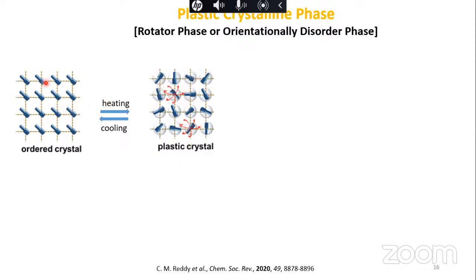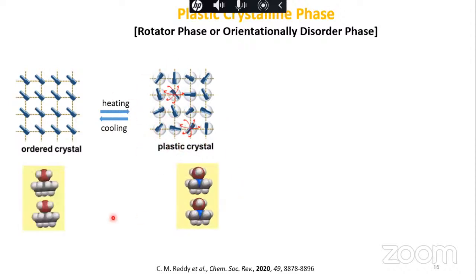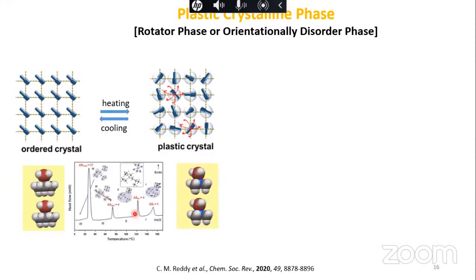So that means you're going from an ordered phase to a plastic crystalline phase. When you have a phase transformation, you need to give energy to the system, and it will absorb the energy and go into a different phase. So this is an ordered one, and this is a disordered one. Since you have to give a lot of energy to make these molecules or ions rotate, this process requires a lot of energy. If you look at the DSC, this peak where you are converting the crystal from order to disorder is very high.